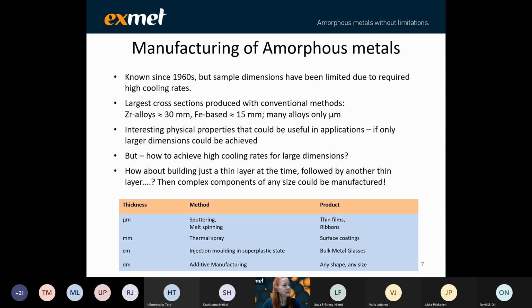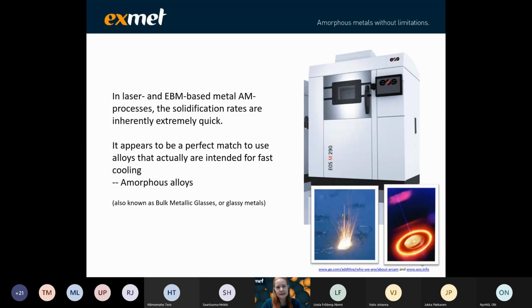So the key to solve here is how to achieve these high cooling rates for larger dimensions. Well, how about just building a thin layer at a time, followed by another thin layer? If that was possible, then one could imagine building complex components of any size, right? And as it happens, these very high solidification rates are inherently there in the laser and EBM-based metal AM processes. So it appears to be a perfect match to use alloys that are actually intended for fast cooling